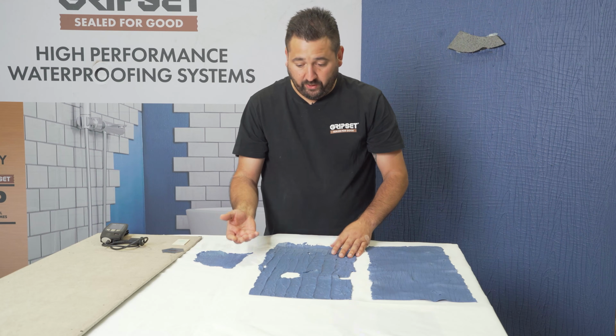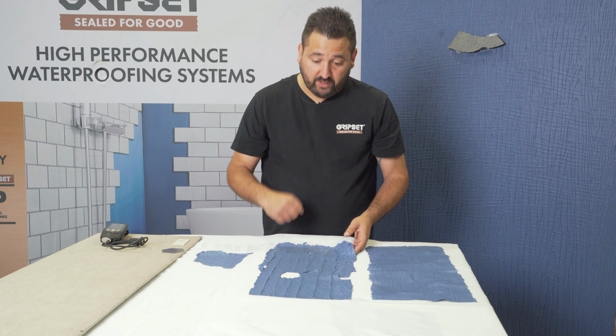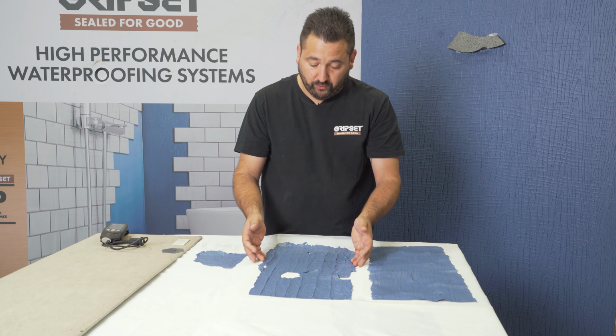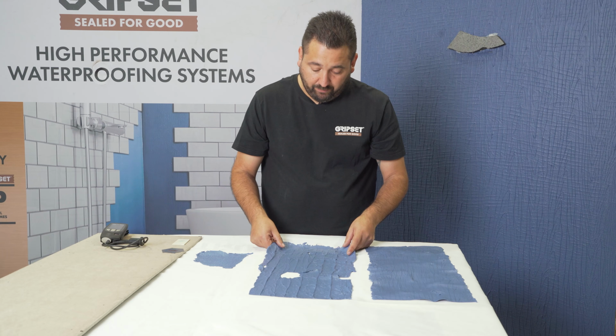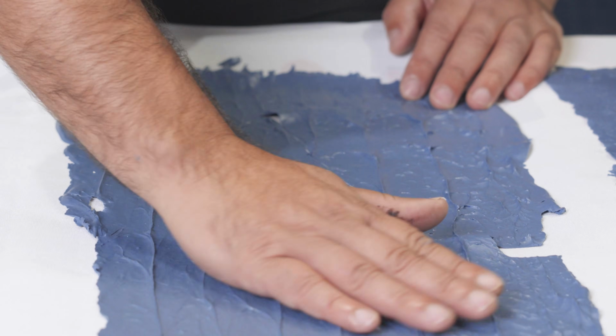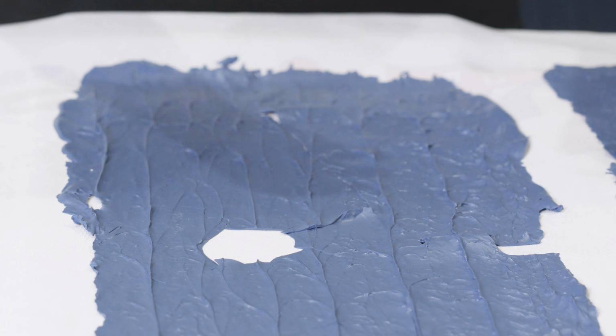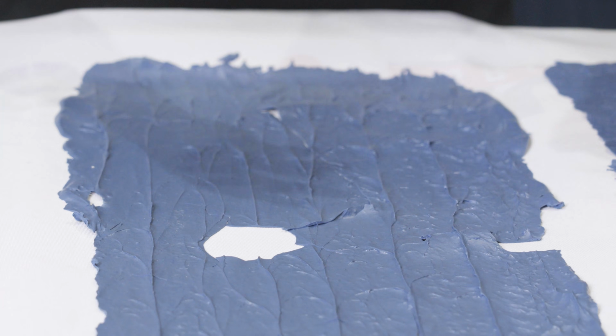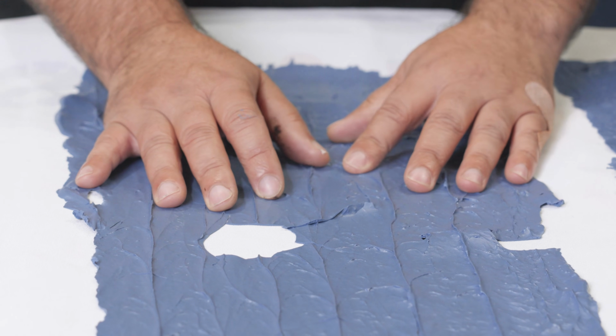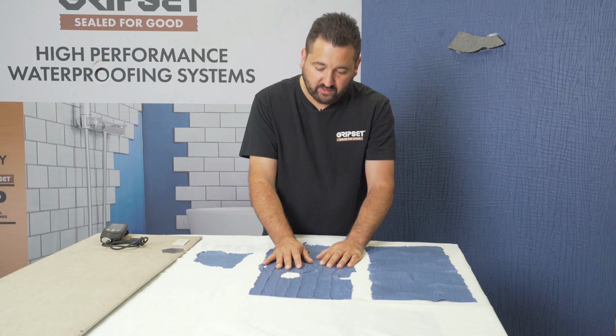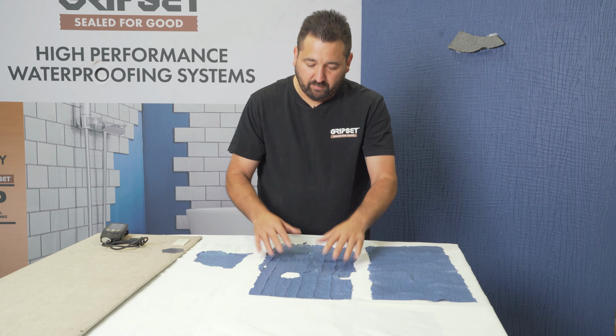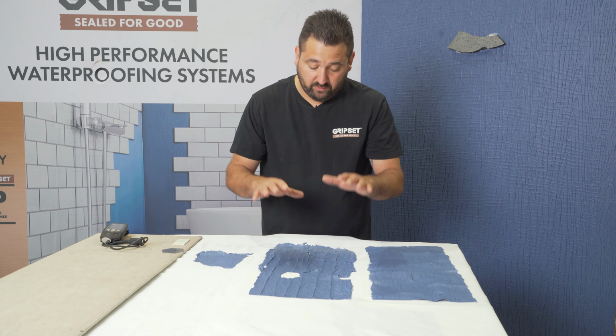That becomes a weak point, and that's quite evident when I peeled it up. It fractured all the way through. So too thick, what happens is the membrane will dry quite well on the surface, then underneath will continue to dry, it'll shrink, puts tension on that surface, and it can then slightly craze. There's other things as well that happen, but generally speaking, that's what the risk is.